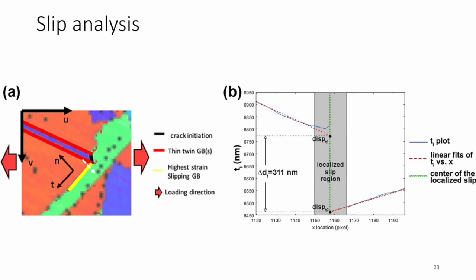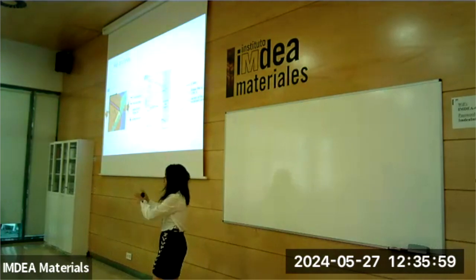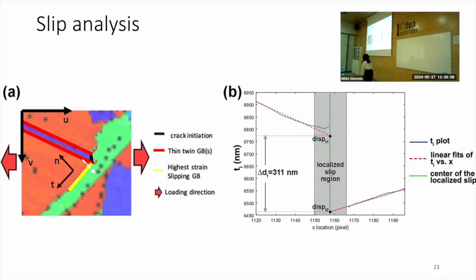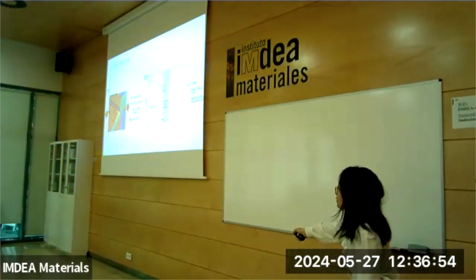Because we did this digital image correlation, we compared how it shifted from image 1 to image 2, and we got displacement. Originally, the displacement is along the U and V directions. Now, if we take the slipping boundary and transform this V and U into T and N directions, where T means tangential and N means normal, just along the direction of the slipping boundary, then if we plot this T value, the tangential displacement, across the slipping boundary along the direction of this white dashed arrow, here we have a T value, and here we have a discontinuity. We take this discontinuity as our slip value. And then we took all of these numbers across this boundary.